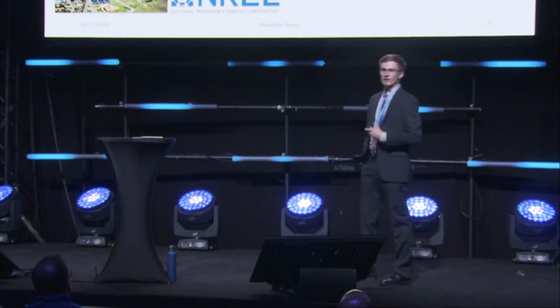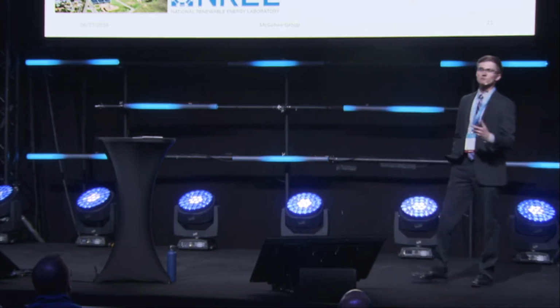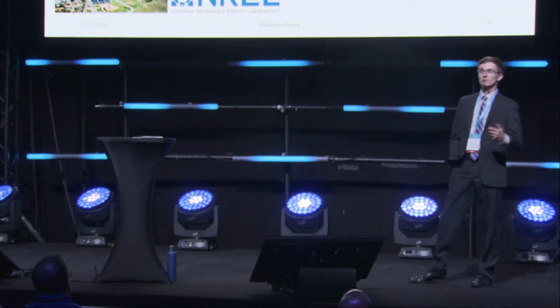Other things that we're actively pursuing: we're working to develop a durable counter electrode by a scalable, cheap process, something like spray coating. One last thing we're working on is developing an electrolyte that is a polymer gel, or potentially incorporating a polymer separator in the electrolyte. This will be very important because, as I'm sure many of you are aware, when you have a vertically positioned window with a liquid electrolyte, you're going to have a massive hydrostatic head pressure build up at the bottom. So doing something that is more of a gel will help prevent any breakage of our seals.